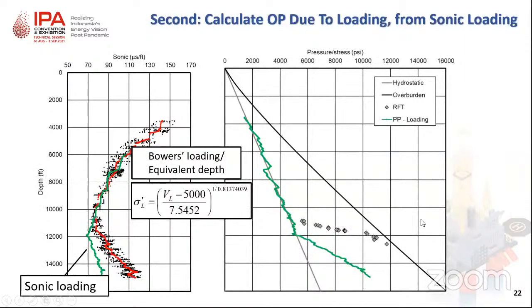After discriminating sonic response to loading, we are able to calculate the contribution of loading to total overpressure by applying analytical methods such as Bowers' method for loading or equivalent depth method. In this well, we use Bowers' method for loading. And this is the equation relating vertical stress and velocity, or reciprocal of sonic. And the green line is the resulting pore pressure contribution due to loading in this well. Loading starts to contribute to overpressure at 12,000 feet down to the TD of this well.